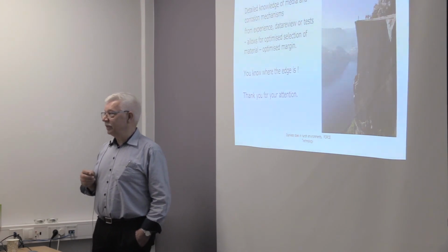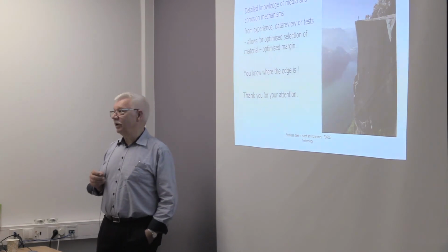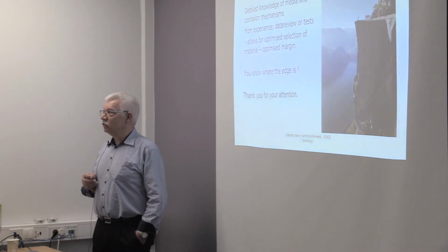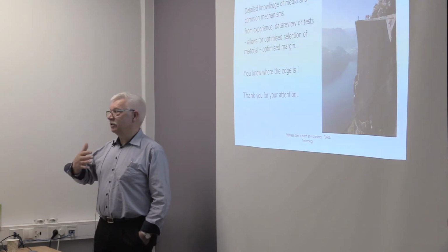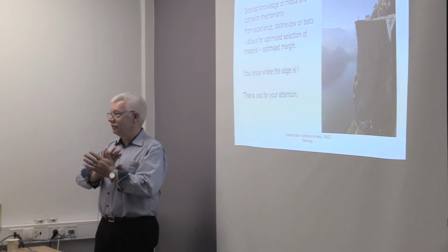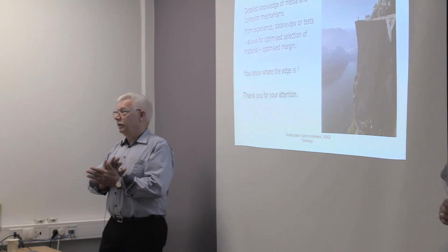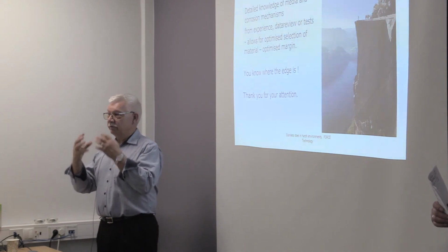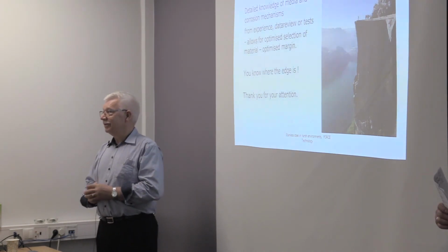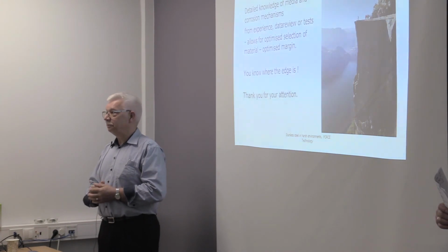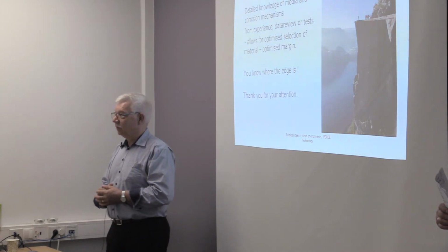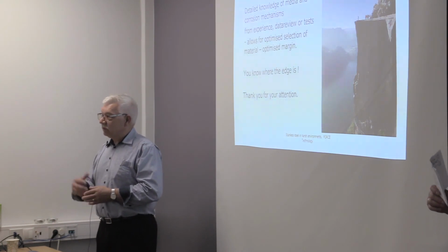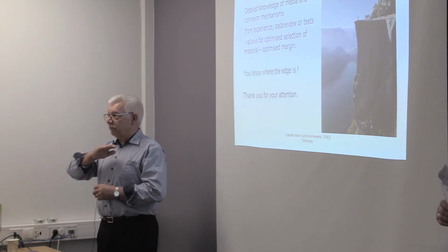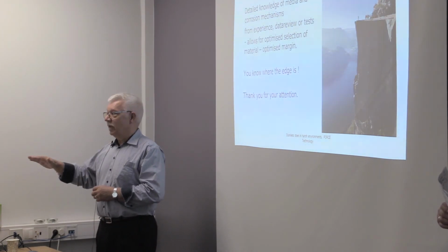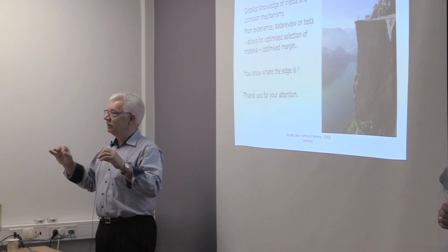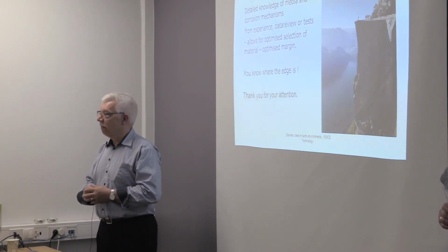And you asked for blasting. I'm not so keen on blasting because it would be okay to remove some large particles, but it will also smash some into the surface and keep them there. Glass blasting is very nice for our eyes, but not for corrosion resistance. So it will not regenerate this. Yes, that's the point in pickling. You get a fully clean surface, and then it will generate its passive layer within short time.